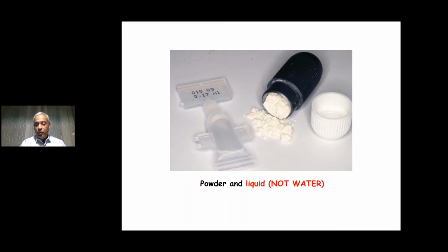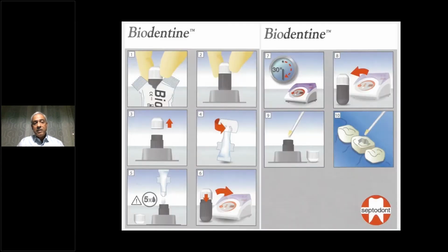So if you want a material with the proper mechanical properties, you need to respect the ratios between the liquid and powder. And if you do not respect this, you will not get the optimal properties of the material. Now, when you get the material, you will mix the powder and the liquid, and it's so precise. You put 5 drops of the liquid into the powder. You mix for 30 seconds with an amalgamator, and then you apply in the cavity without any prior preparation or etching.